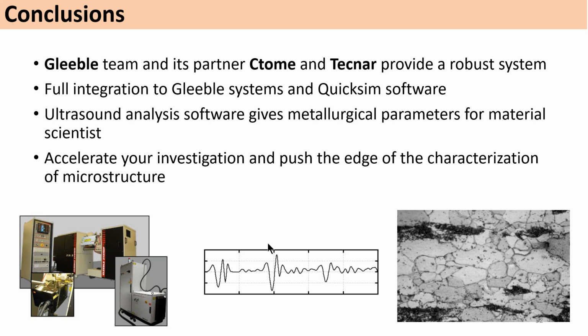Okay, thank you. A question here says, how do you compare the sensitivity of the laser ultrasonic with conventional piezo-based methods? Okay, well, I would say piezoacoustic sensors are different in essence because they are generating a pulse of a narrow frequency bandwidth. And so Lumet, by generating those waves using a laser, can generate a pulse with a much broader range of frequency. So unless you have an array of piezoacoustic sensors, Lumet will always be more interesting for metallurgical studies, thanks to the fact that we have access to the frequency dependence of ultrasound pulses.